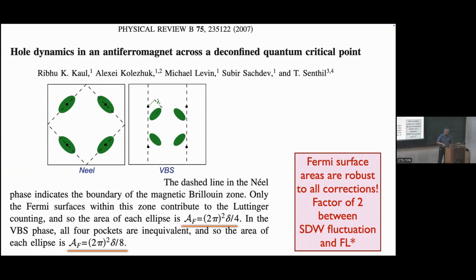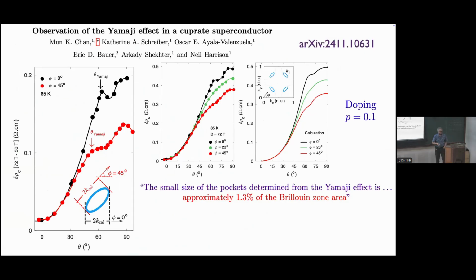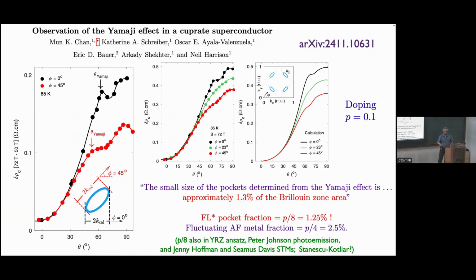And of course, just to drive home the point, in 2007 we wrote a paper emphasizing this area difference. It should be p over 4 for the antiferromagnet. This is a descendant of the FL* state, but the broken symmetry of the valence bond doesn't affect the Fermi surface. It should be p over 8. Okay, and of course, I'm sure you're calculating ahead. What is p over 8? Well, 1.25% is the prediction of p over 8, which is very close to 1.3 and quite far from all the other models.